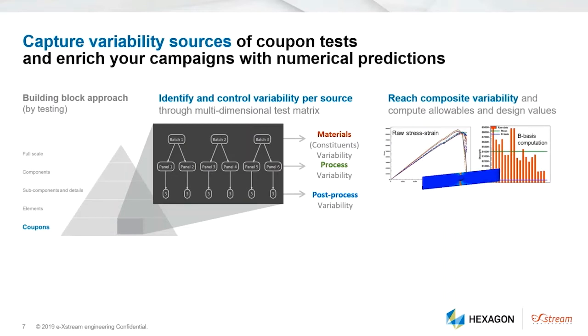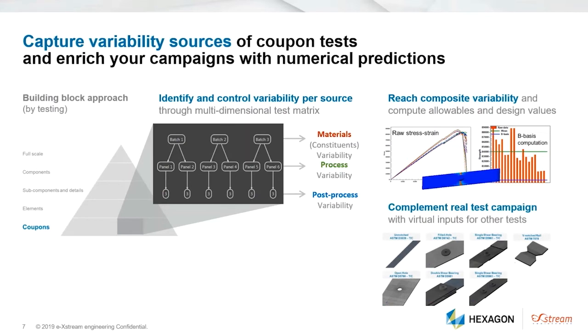Simulating contribution of those variability sources at coupon level provides a cloud of response, allowing to compute virtual allowables and design values. Once each variability source is identified and quantified to capture average values as well as allowables such as A basis and B basis, the model benefits from a greater trust. It means that for many stacking sequences and in many mechanical configurations, the variability is captured. From this point, the strength of this approach is that new stacking sequences and test configurations are now virtually accessible with few simulations. In other words, allowables for other stacking sequences and additional tests can virtually be computed to lighten real test campaign. This is a serious plus when looking at the 1,000 coupons test required for material certification.